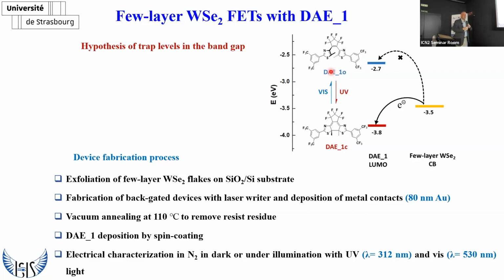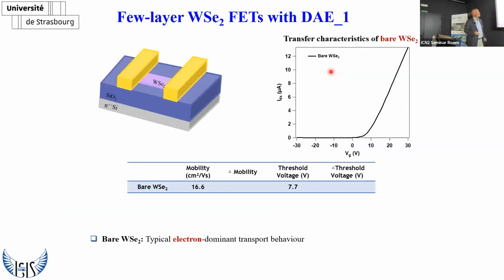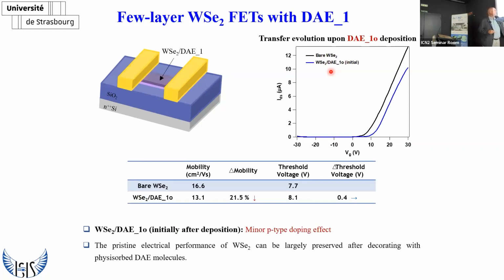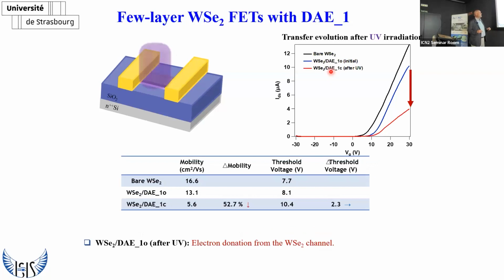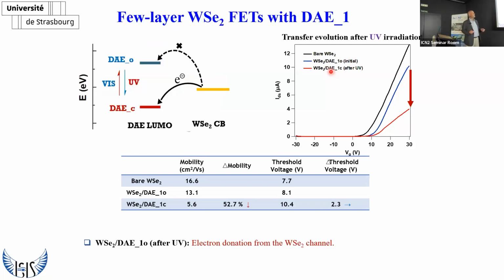Electrical characterization is done either under illumination with UV light or with visible light. So we start from the bare tungsten diselenide with a given mobility. Once we deposit the diarylethene in the open state, where it is not trapping charges, we have a 20% decrease in the field effect mobility. And then at this point, we illuminate with UV light, so we close the diarylethene from the open to the closed state. And you can see that we create traps such that we have a decrease in mobility of 50%.